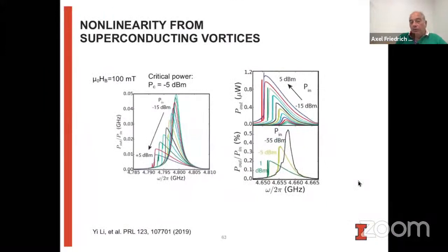So I want to show one last thing that's kind of interesting. Now, all the measurements that I've shown you so far were at really low powers. So we're talking nanowatts, to avoid any significant heating of the resonator, which degrades the power. But if you just look at the superconducting resonator, it actually has a very pronounced nonlinear behavior as we increase the power. So here you see the transmitted power as a function of frequency for different power in the resonator, while we apply a magnetic field. And you see that going from a nice Lorentzian kind of peak here, we get this fold over behavior, which indicates strong nonlinearities. And this strong nonlinear behavior is directly related to introducing vortices in the superconductor.